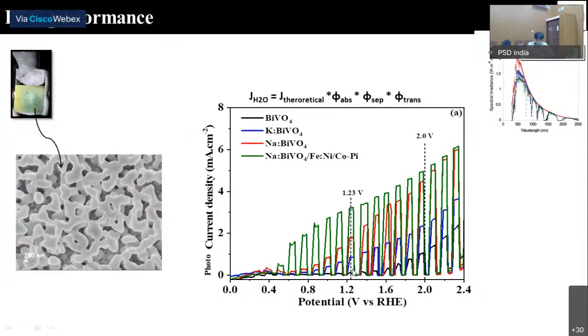Now, as soon as we dope it with potassium or sodium, it enhances. For the sodium, it is high, and then as soon as we put the surface co-catalyst, it further increases. So what are the factors which play a role in the enhancement of water splitting behavior in the doped bismuth vanadate system? For that, if we see our JH2O equation, JH2O is equal to the theoretical current density multiplied by the light absorption efficiency, charge separation efficiency, and the charge transfer efficiency. Now, these individual efficiencies play a key role in the water splitting behavior of the bismuth vanadate system.